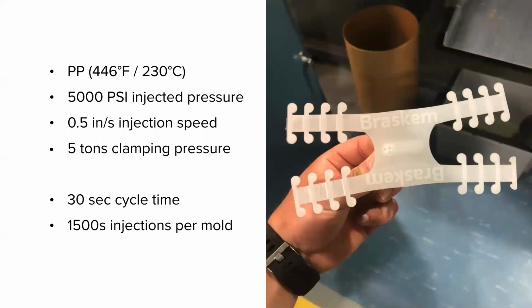Yes. What melt resin were you using? So this was a polypropylene resin we were using. To get the best results, in lowest pressures, you want to use something that has a rather low viscosity. You don't want to have a lot of resistance to flow because that's just going to mean more pressure. So if you can use a higher melt flow resin, I think you'll have a little better success with the fill out of the mold. I believe in this case, we were around a 30 or 40 melt flow. But again, those melt flows are going to be correlated to the specific resin. So if you're using ABS or polycarbonate or something else, you'll need to just try and go on the higher end of the melt flow range.